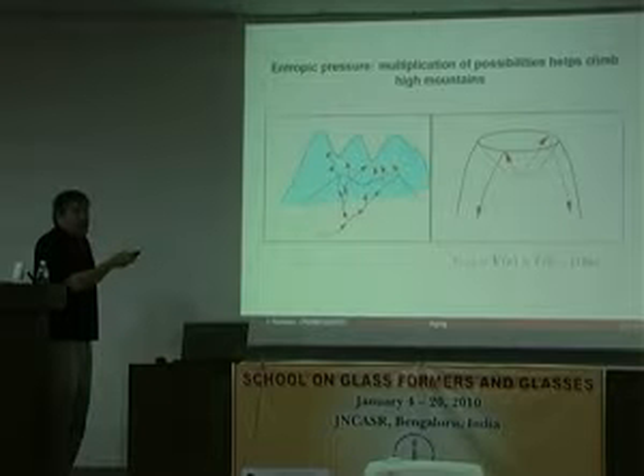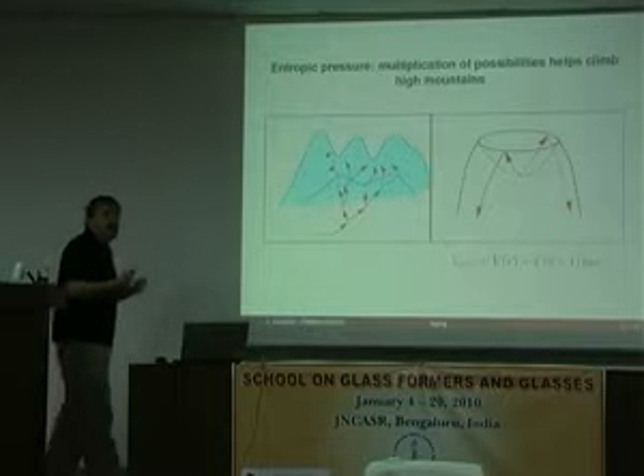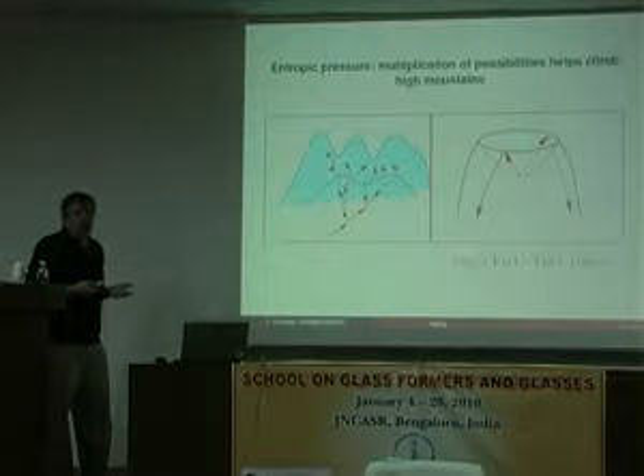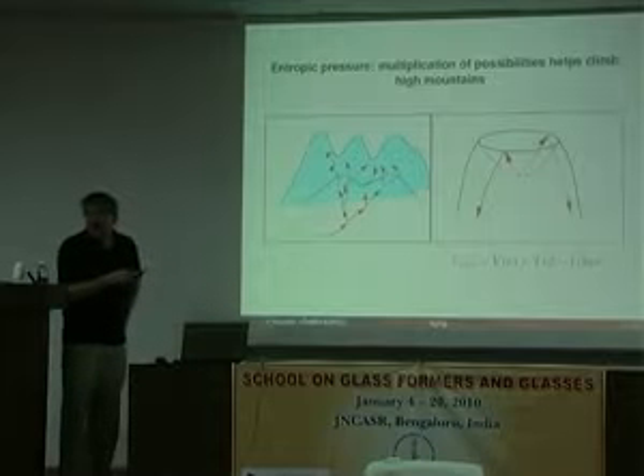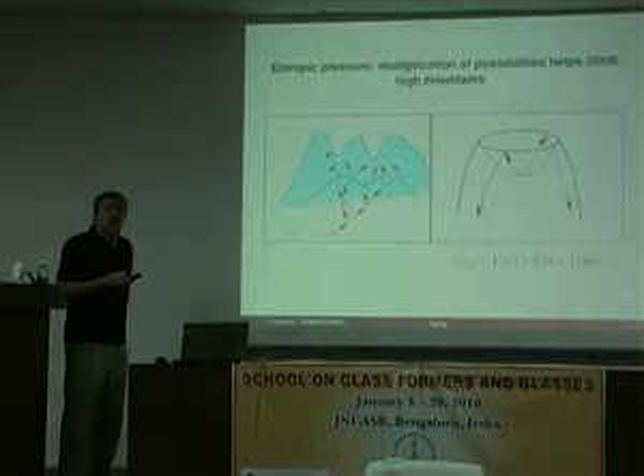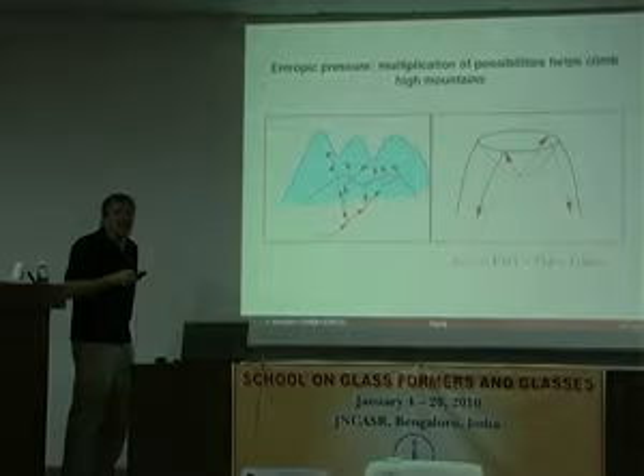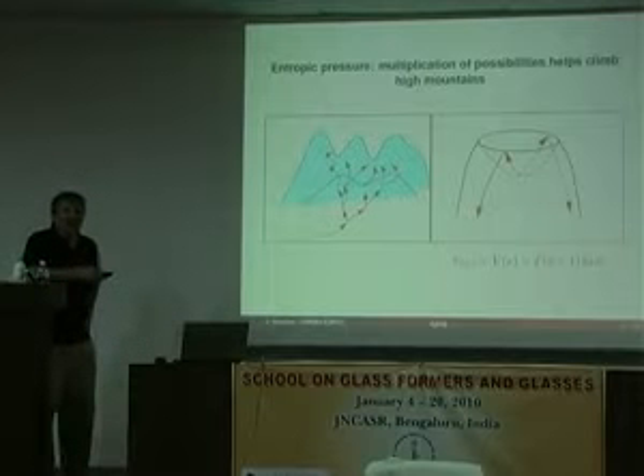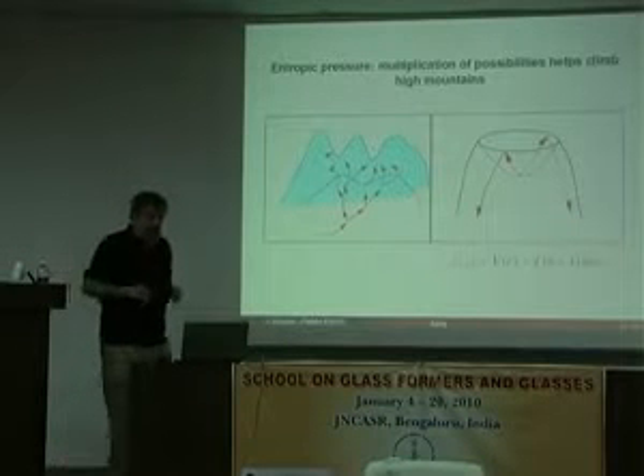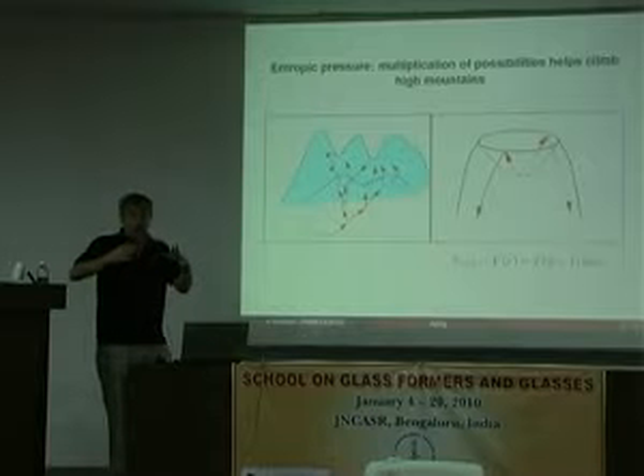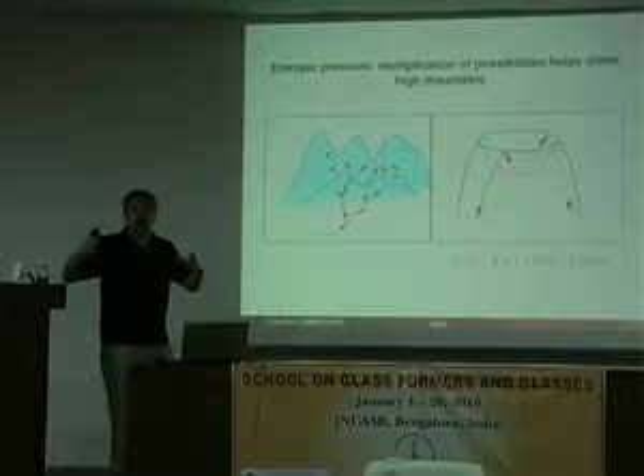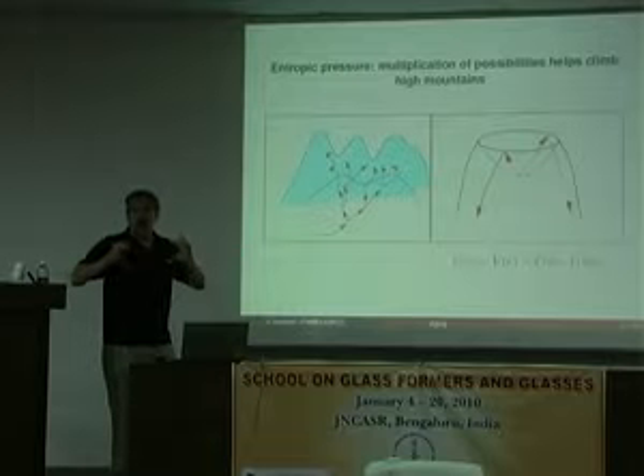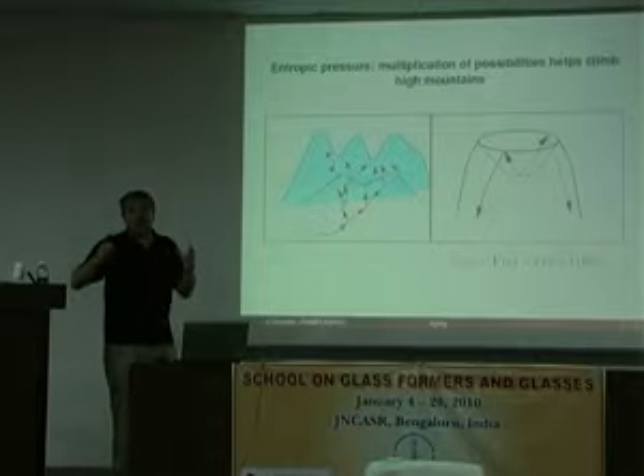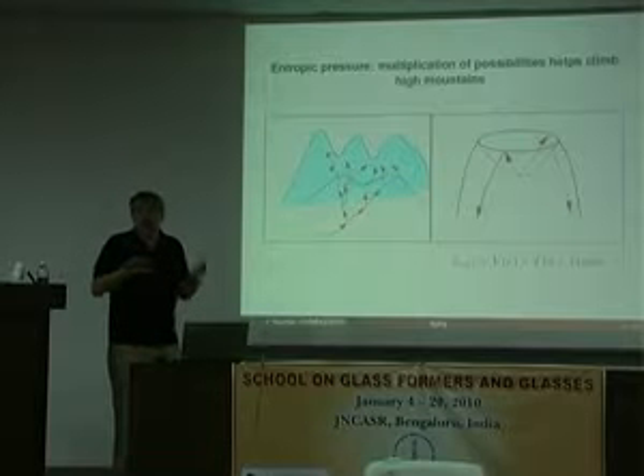This is like how activation works. So it is normal to think that because there are so many trials per successful path, having many possibilities is a good thing. And you can prove it. And let me tell you a nice exercise to do. The mountain is supposed to be represented... It would be representing a situation, for example, where you're trying to nucleate a bubble, as I said before, but at each progressively larger radius of the bubble you're nucleating, you have many options and not only one. So as soon as the number of options you have when your bubble is growing are many-fold, you're gaining more than the mere free energy of each one of those. So you're gaining with the complexity.